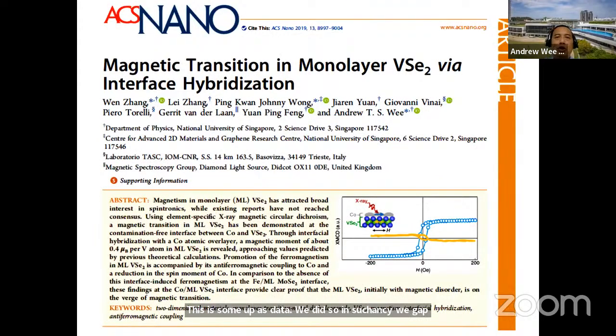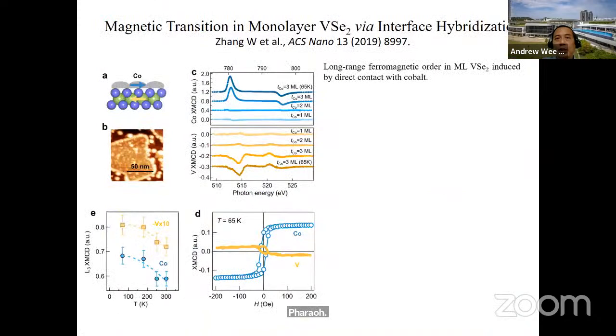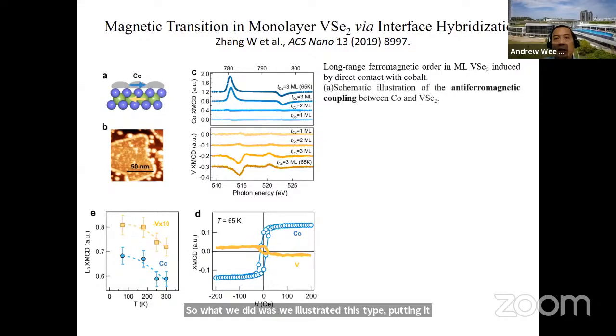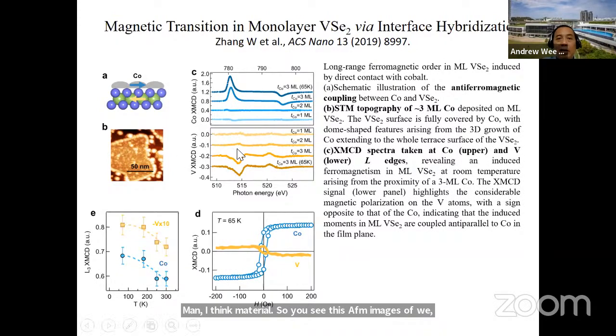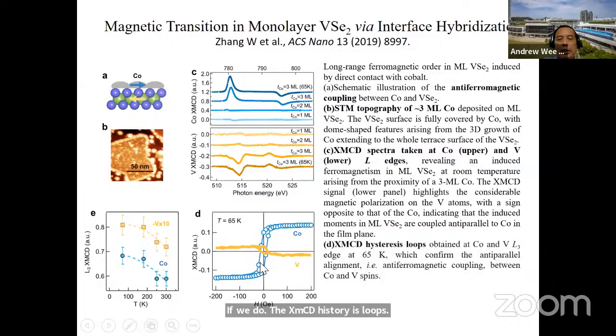Now, although we have shown no magnetism in 2D vanadium diselenide, we showed that we could get these hysteresis loops, this is XMCD, if we have interface hybridization with a ferromagnetic material. So what we did was we illustrated this by putting it in direct contact with cobalt, which is a ferromagnetic material. So you see these STM images of when we put about 3 monolayers of cobalt, and the XMCD of the L edges, you see this is the vanadium and this is the cobalt, and you see the absorptions are in opposite directions, indicating this is anti-ferromagnetically coupled. And hence, if we do the XMCD hysteresis loops, you get these loops in opposite directions. So although vanadium diselenide is non-magnetic, it can be easily magnetized.